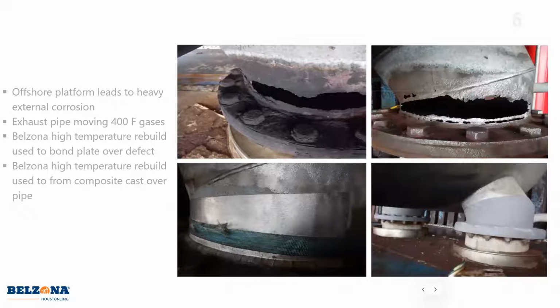So going into one, this is an exhaust pipe that was handling 400-degree flue gas coming through. And you can see this is one where you might think, man, we're going to have to shut down, unbolt this flange, total replacement, or cut it out, weld it. But we were able to come in and do a bonding of a plate. We used our rebuild material, a high temperature paste grade material, and we bonded a plate over the hole after we'd done some surface prep and cleaned up the metal.